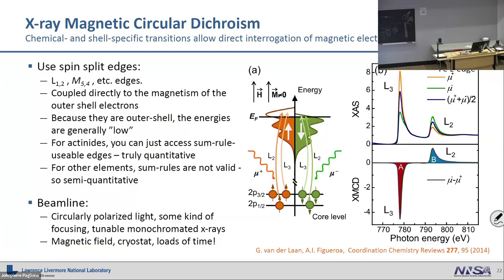The idea is that you come in with your X-rays and you're going to excite one of these core levels up into the band somewhere. So you're resonant right at an edge. And the difference here is that if you have a magnetic structure, you have a spin split band. So you have a different spin up band and a spin down band. So depending on which one of these polarizations, either spin up or spin down, you're going to excite into a different channel, basically, into a different band.